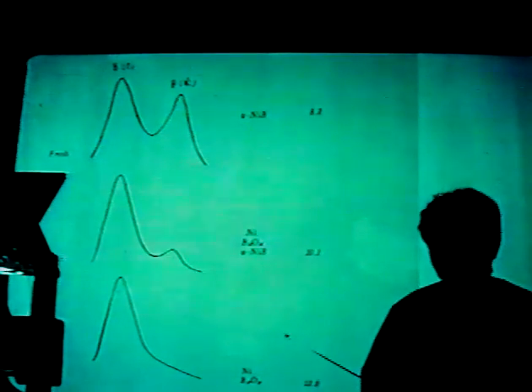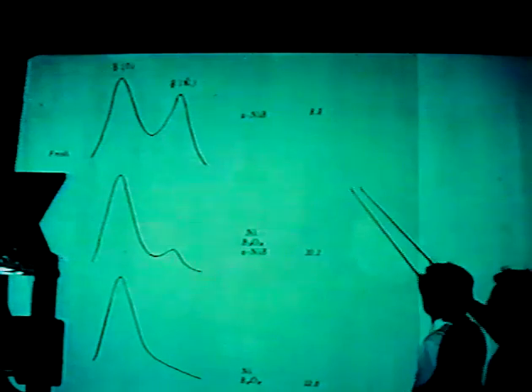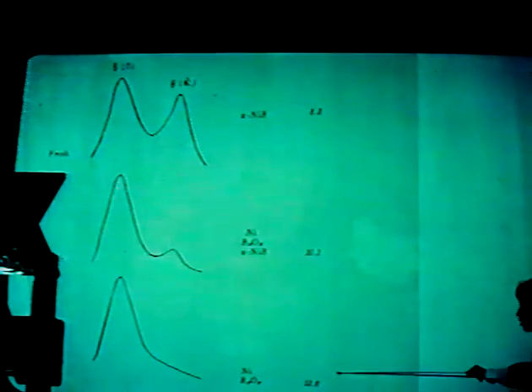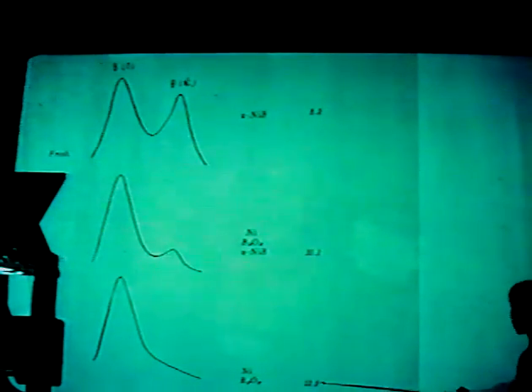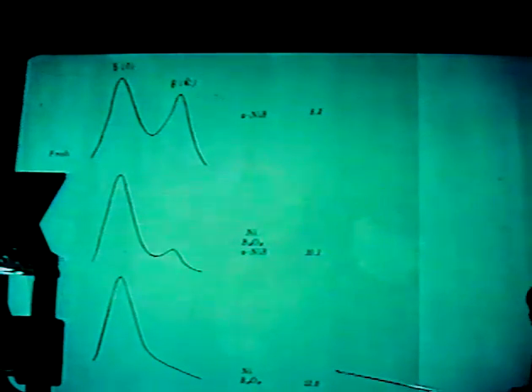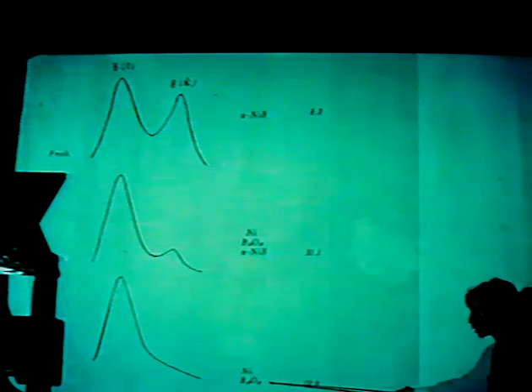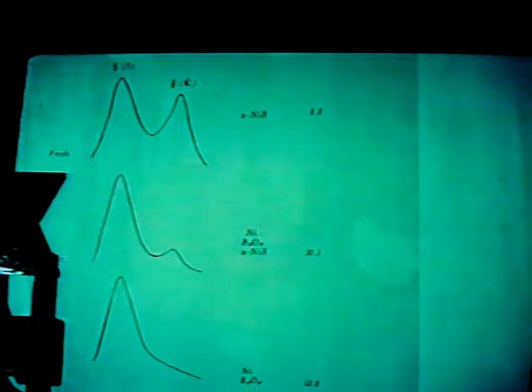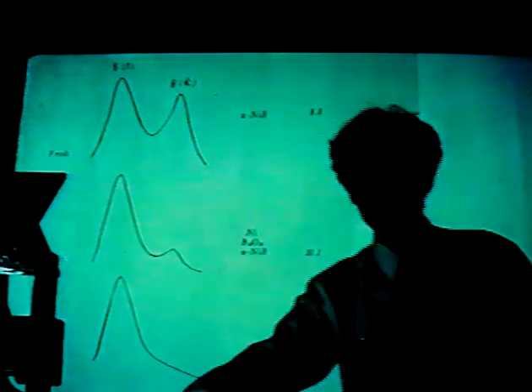So the larger number of nickel metal sites and the great interaction between nickel and boron can account for the substantial increase in methanation activity. In summary,